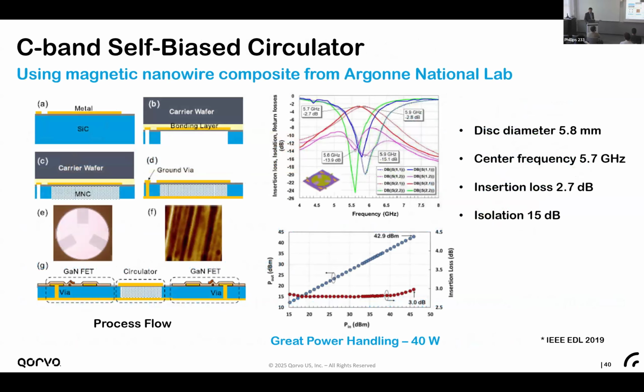And we were able to make a C-band self-biased circulator. The material is from Argonne National Lab. It's based on nanowire composite. Basically, you take AAO templates, porous, and you do electroplating of cobalt or nickel, iron cobalt or iron nickel nanowires in these AAO templates, and magnetize it once in a strong magnetic field, and the magnetic field will stay there. And you insert this piece of disc into the backside of the GaN MMIC.